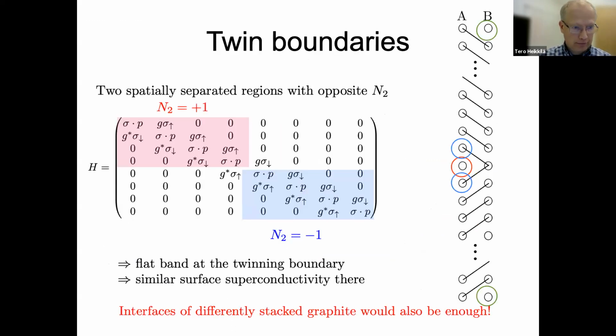Okay, I realize that I have used already a lot of time, so I just mention that one way to get these flat bands not on the top or bottom surface would be to make so-called twin boundaries where the stacking changes along the way, so that you would have these localized states here, and in this case, the delta would become also finite inside this twinning boundary.